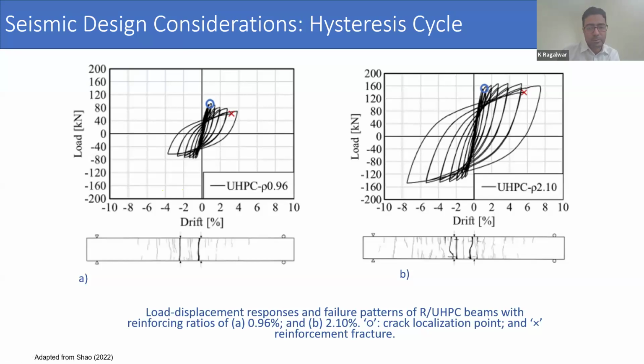lower reinforcement as well. On the other hand, in the beams that fail after gradual strain hardening, and strain hardening can occur in beams on account of higher reinforcement, as well as the ratio between the tensile strength and the reinforcement provided. So here the hardened reinforcement carries greater flexural tension force than it did at the point of initial crack localization.